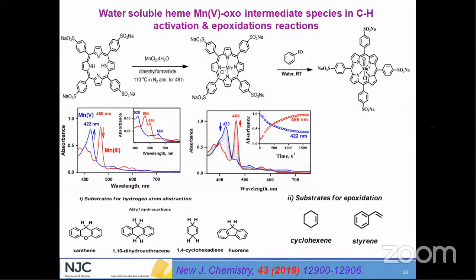Now, since we are sure that it is a manganese 5 oxo species, we thought of doing some C-H activation reactions. We selected these substrates for C-H activation: xanthene, dihydroanthracene, cyclohexadiene, fluorene, etc. Besides that, because recently a lot of work is being done with cyclohexene as a substrate, we tested it too. Cyclohexene is a very beautiful substrate which can undergo epoxidation as well as C-H activation, to give an alcohol, cyclohexenol, right? Since it was fascinating, we also tested cyclohexene and styrene, and styrene is a popular substrate because it will give epoxide.